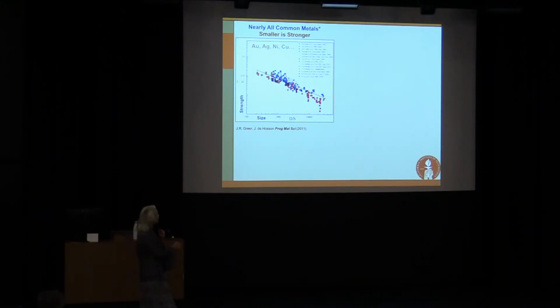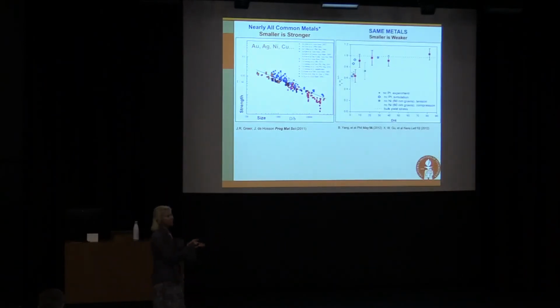So now, if you look in these metals in their single crystal form, and you plot their strength as a function of size, you see this tremendous strengthening, again, a log plot. And what that tells us is that if you take a chunk of gold, which we know to be very malleable, and then reduce its dimensions to 200 or 100 nanometers, it becomes as strong as steel. Wow, well that's a lot of strengthening, right? But now, take exactly the same metals, gold, platinum, copper, nickel, and deposit them using a different technique. All of us here do nanotab of some sort.